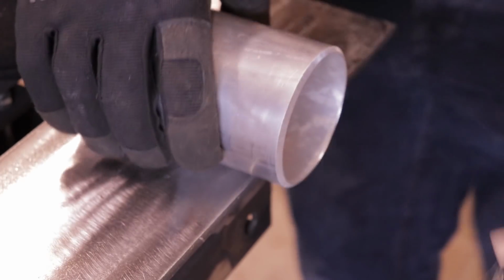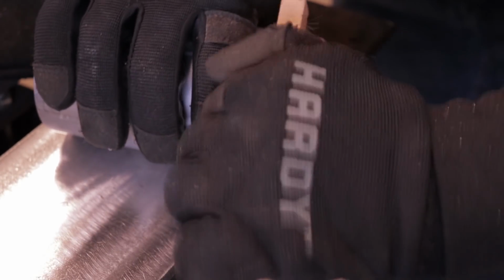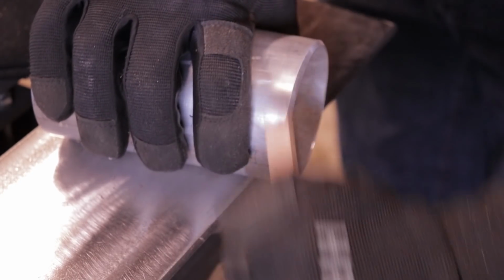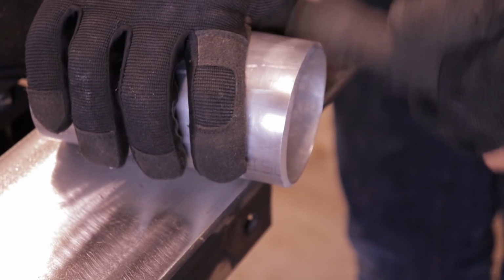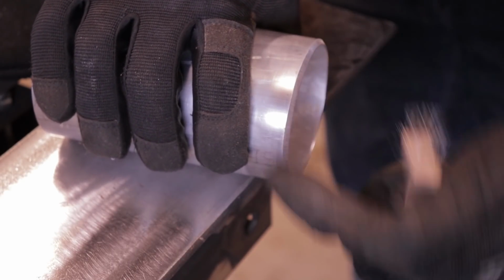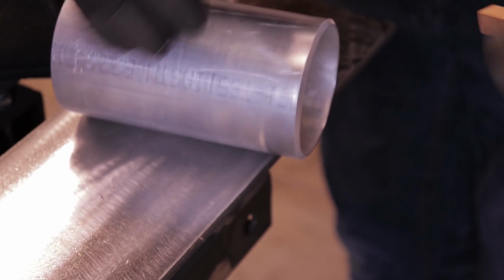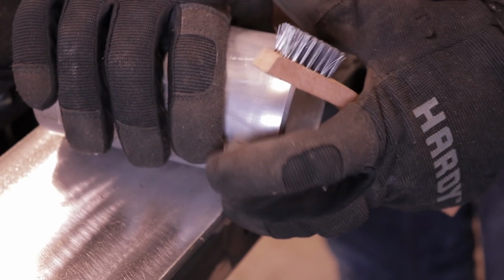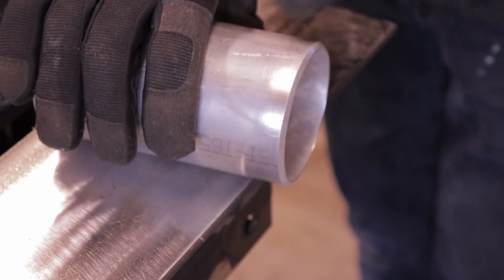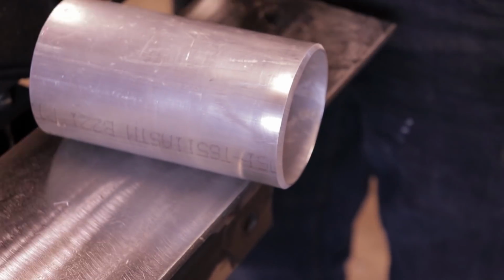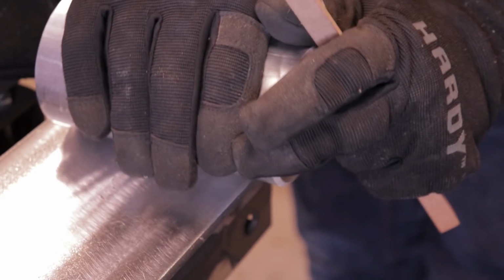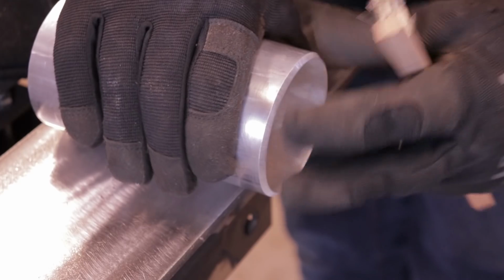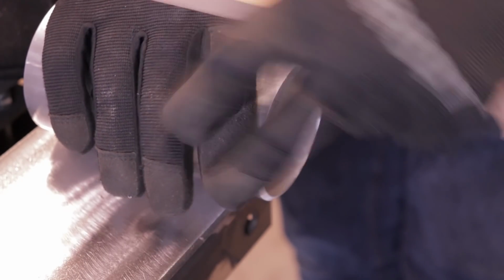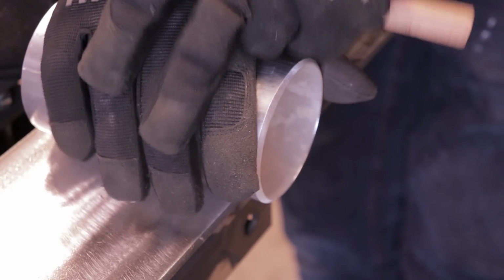So if you're going to be welding, especially on a test like we're pretending this is, you really want to wire brush it all. And the reason why you're wire brushing it, it breaks off the oxide layer, but you're not just removing the oxide layer, because with aluminum the oxide layer actually just forms right back on as soon as it gets scraped off. It's constantly growing and adding an oxide layer, but if it's been sitting around, dirt and debris, anything that's in the shop, and especially if it's been outside, is landing on top of the oxide layer of the aluminum, and then it's kind of growing around those little microscopic specks and all that stuff.